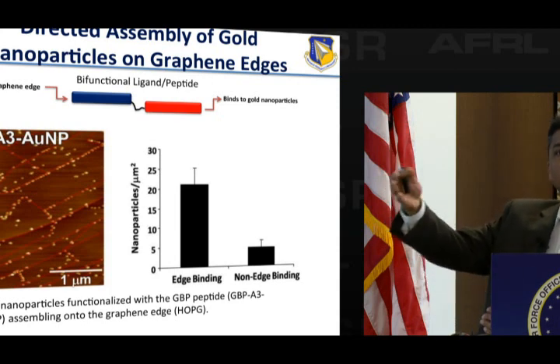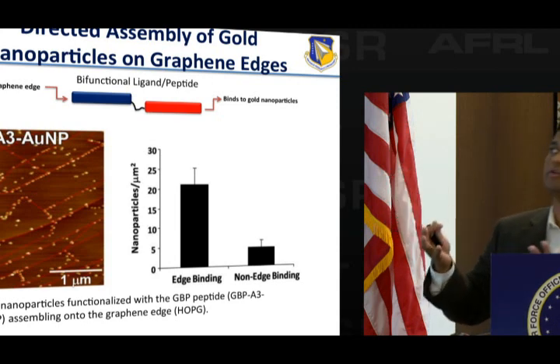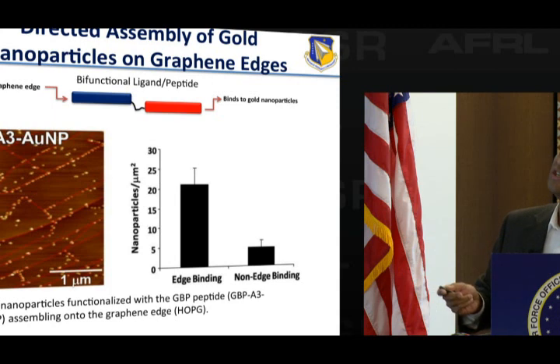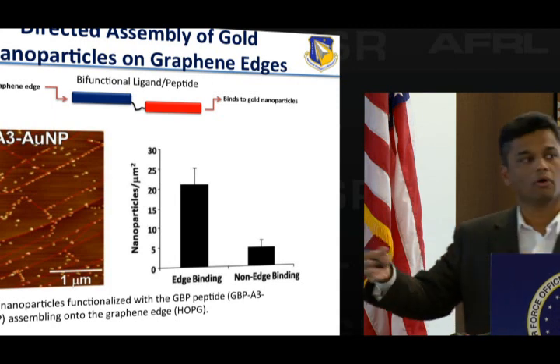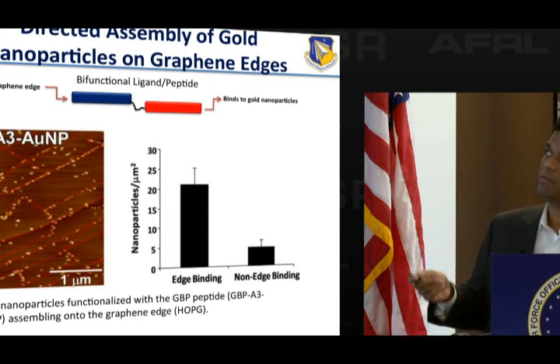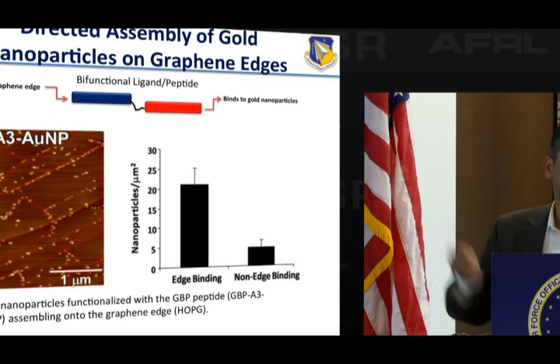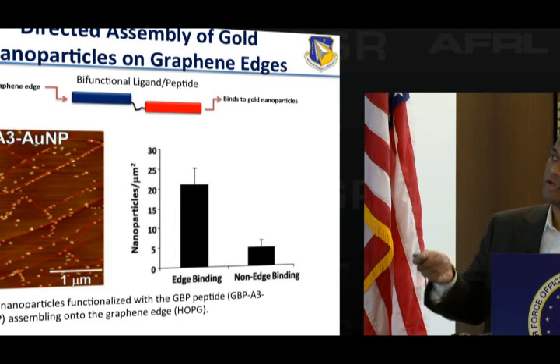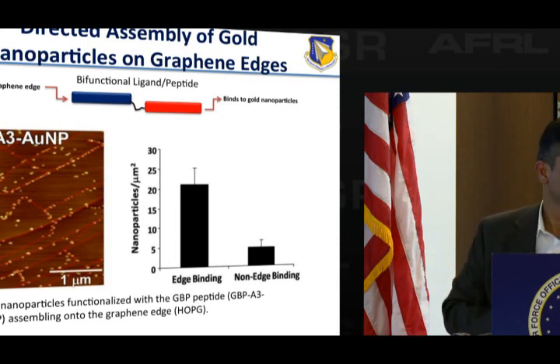And you can build upon this. If I would really want to create a hybrid material, I can think of putting things together where I have one that likes to bind to graphene, maybe something else likes to bind to gold or some other material of interest. I can mix it onto the surface, and here is now gold nanoparticles actually assembling on the edges of graphene sheet. I don't know whether you can see the red lines, but we have mapped the edges using AFM, and we can show where the gold nanoparticles go.